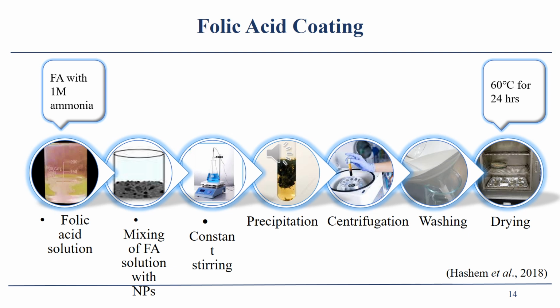The next step would be the coating of the prepared nanoparticles with folic acid. 0.2 gram of folic acid will be dissolved in 1 molar 40 ml ammonia and will be added to the prepared nanoparticles. For a further 30 minutes, the mixture will be stirred constantly until a precipitate is formed. The precipitate will be separated by centrifugation and washed thrice to remove excess ammonia. Then it will be dried in an oven at 60 degrees for 24 hours.